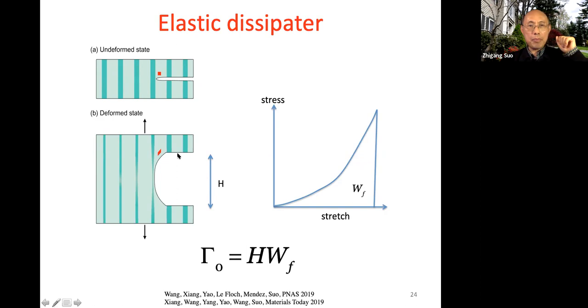Now look at what happens. So mark one material particle by a square. I'm gonna put a square marker here. So we know because this matrix is so soft, when I load this material, I will have an enormous blunting because the matrix can shear. So I represent shear by a parallelogram here, the material sheared this way.